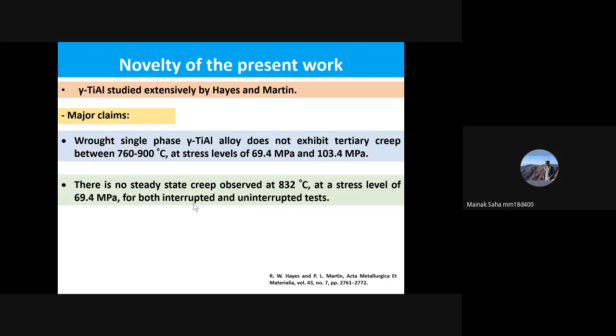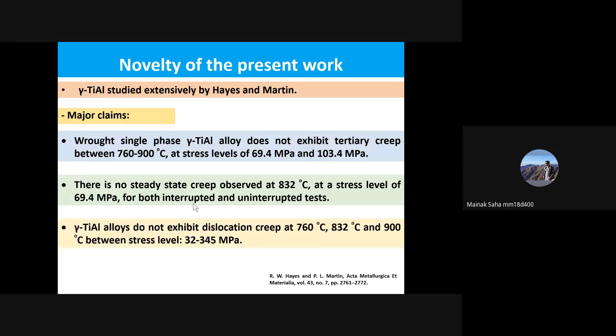the fracture. And the third claim was that the gamma TiAl alloys do not exhibit dislocation creep at 760, 832, and 900 degrees between the stress levels of 32 to 345 MPa. This forms the novelty of the present work, because the present work mathematically tries to review whether the claims are really true or not.